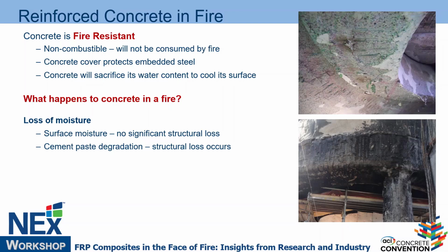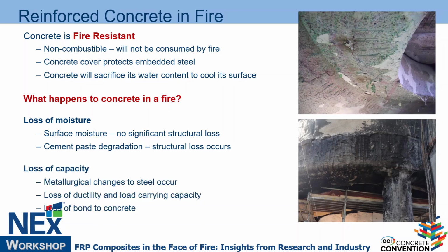But degradation doesn't mean it's doing nothing. It's really sitting there most of the time. If it didn't spall, it's sitting there providing insulation to the internal reinforcement. And that continues with time until at some point the temperature is so high that you get spalling, right? And when that happens, the temperature of the steel would rise, even with the concrete in place, right? Because the temperature would reach the steel. There is some delay between the fire temperature and the steel temperature just because of the cover. But once you lose the cover, it starts rising significantly.